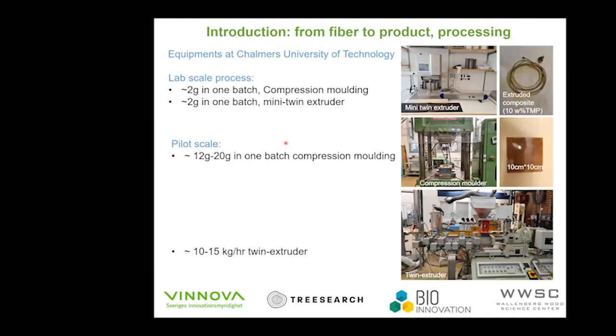Here I have a brief introduction to the equipment that we are using at Chalmers. In the lab scale process, we have a mini twin extruder that we can put about 2 grams in one batch, and here you can see a product of that. In the pilot scale that is available in the material engineering department, we have a compression molder with about 12 to 20 grams of material, giving a 10 centimeter by 10 centimeter product at the end. And we have a twin extruder that we can feed 10 to 15 kilograms per hour.